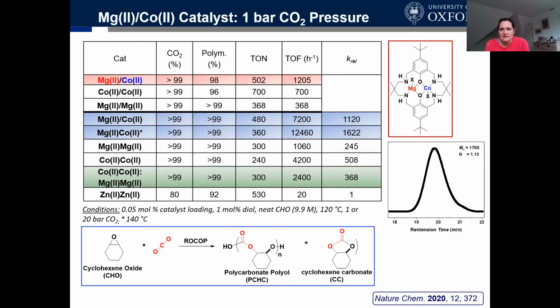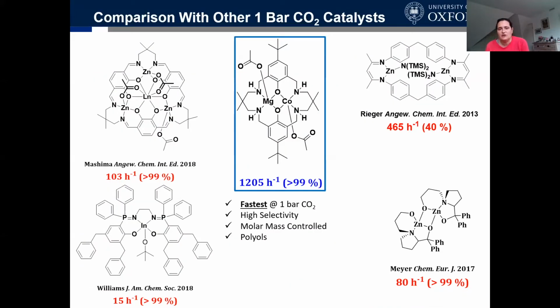Now here I'm just giving you relative rates, so you can see now with the better catalysts we're about 1,000-fold more active than we were with zinc. So this probably doesn't mean too much to you as numbers unless you understand how the rest of the field is performing. And so here I've given you some good other catalysts that are out there in the field, and you can see that really this is the fastest catalyst at 1 bar. It's very selective, it gives you good control of molar mass, and it makes the right type of product with the hydroxyl end groups. I don't want to go through all the examples, but you can see there that most of them are giving turnovers around 100, and then a very active one with zinc there is about 400, but it's not very selective. It has quite a big selectivity problem at 1 bar.